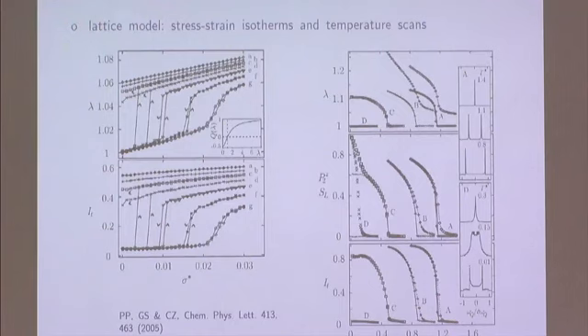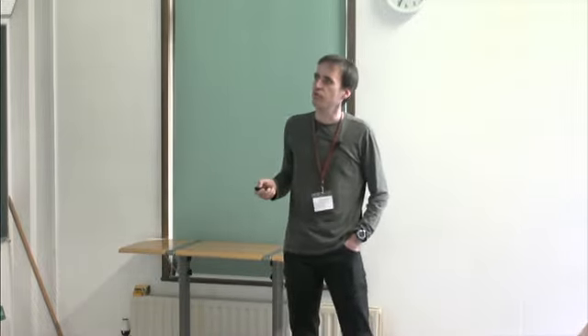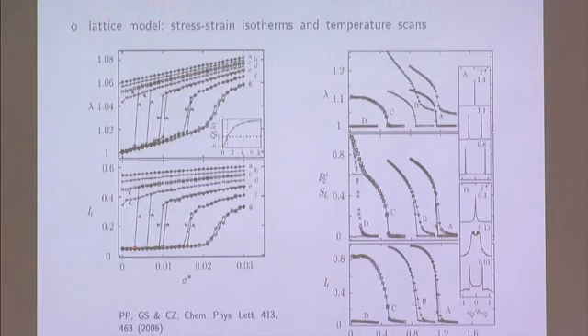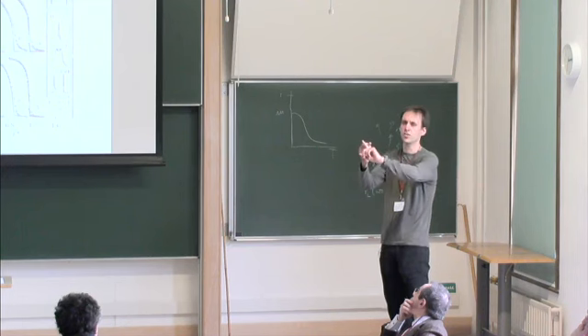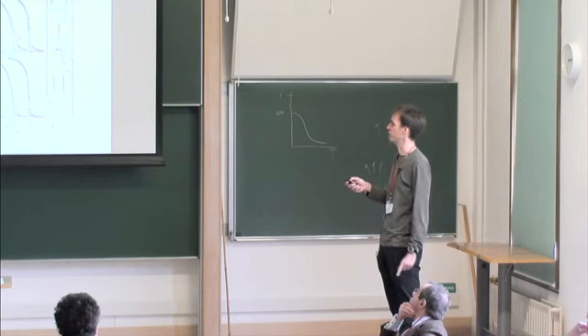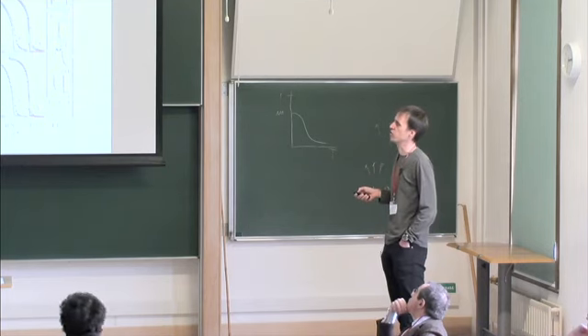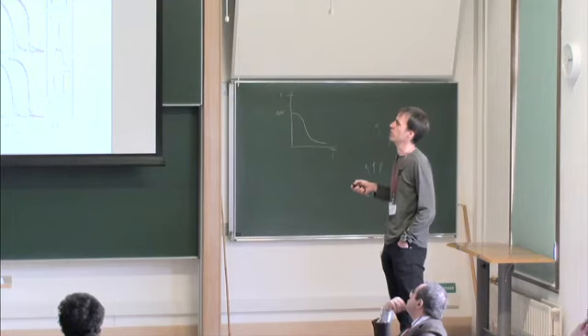And again, also here in the inset, you can see the Q of lambda dependence: no deformation, no Q, and this is actually calculated as P2 of cosine theta averaged on a deformable sphere. So you can deform it to an ellipsoid to have a positive value, or compress it to have a negative value. What we also see here is a simulated birefringence. If you put your sample in between two crossed polarizers, then the measured intensity of transmitted light will be basically just proportional to P2, to the degree of ordering in your system, and it's coherent with what's shown in the upper plot.